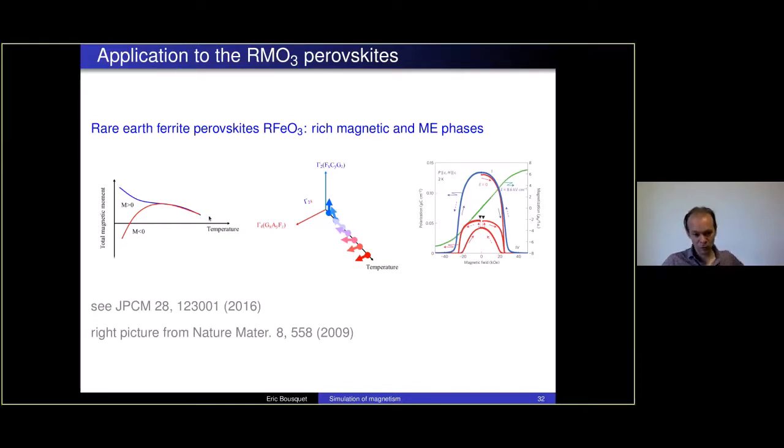So it means that you have a Pnma phase, like the yttrium chromium oxides. You have a weak ferromagnetic canting, and this weak ferromagnetic canting can either be amplified when you cool down the temperature, or it can be decreased and even reversed with respect to the initial state. And this is due to the interaction with the rare earth f electron that I'm going to show you after.